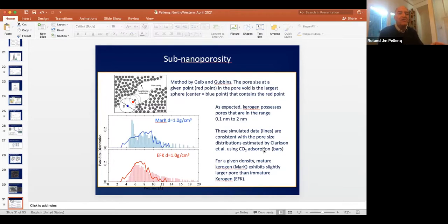And the way to put it back at constant temperature is called measuring an adsorption isotherm, which is used for any porous material, including cement. It could be nitrogen or CO2. And CO2 is especially good to probe this 1 nanometer scale. Anyway, when we do the CO2 adsorption and calculate the pore size distribution, we are right on top of what the simulation is predicting.